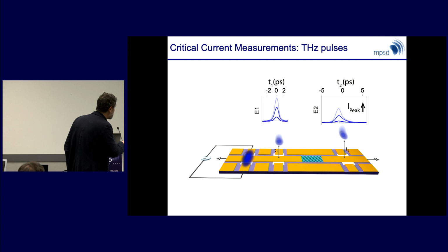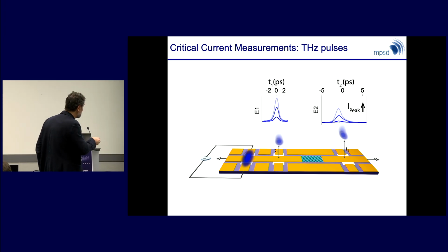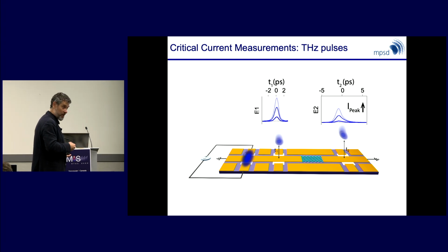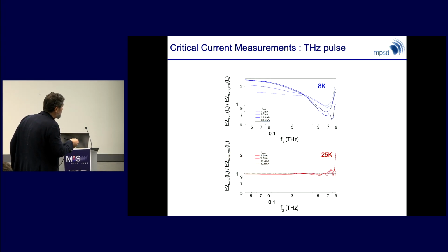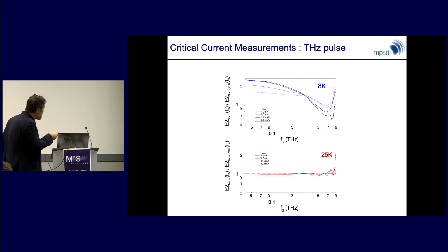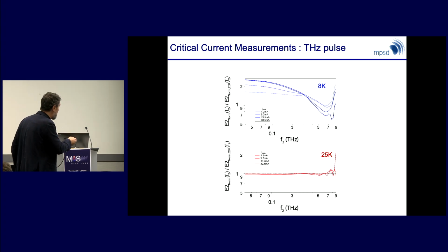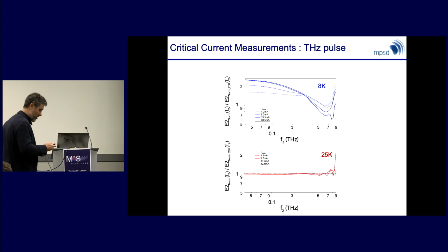Now what we can do is change the fluence in this launching switch. You probe it here and you do the experiment 3 times. The incoming current is either 1 number, 2 times that number, or 3 times that number. And here we measure the transmission in these situations. Again, equilibrium terahertz critical current. What you observe is that, for example, at 8 Kelvin, well below TC, the 50 gigahertz response drops from 2.5 to 1.8, say. When you go above TC, there's no effect, because the metal has a much more linear current response at these frequencies.